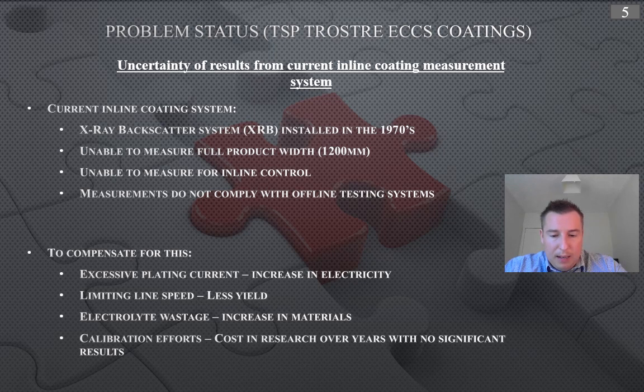When I went down there to do an investigation, I also noticed that the system is only measuring the center line of the product. So I think a measurement system for the full product width would be very beneficial for them. And because the current system is installed at the end of the production line instead of straight after the process, it renders inline control implementation very difficult. So to compensate for this problem of ensuring the coating meets its weights, they use an excessive plating current, which is an increase in electricity. They're also limiting the speed that the production line is run, so they're getting less product output.